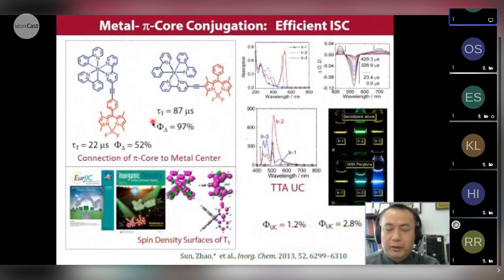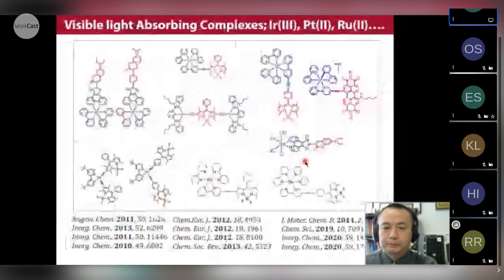With similar method, we prepared the different complexes. For these two examples, we can observe similar strong absorption of visible light, but the intersystem crossing efficiency is very different. For this one, with the direct connection, we have a higher intersystem crossing quantum yield. But for this one, we have much lower intersystem crossing quantum yield. So we cannot simply connect organic chromophore to a metal center to prepare efficient photosensitizer. We have to use proper linker to ensure we have efficient intersystem crossing.